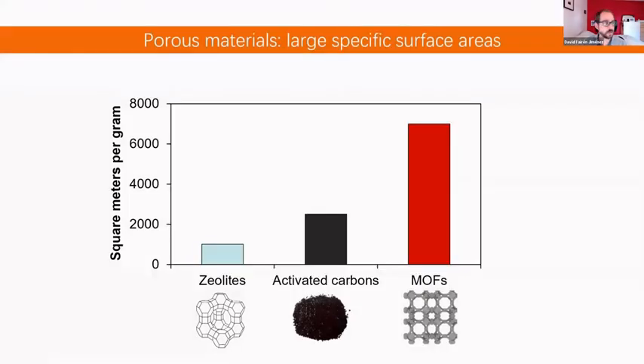Now, remember, high surface area doesn't mean it's going to be good, because this material also probably is going to have a very low density, okay? The same with an activated carbon. An activated carbon with 3,000 square meters per gram will have very low density, and many times these materials are not going to be optimal for some industrial applications. Maybe for some of them, but not for all, okay?